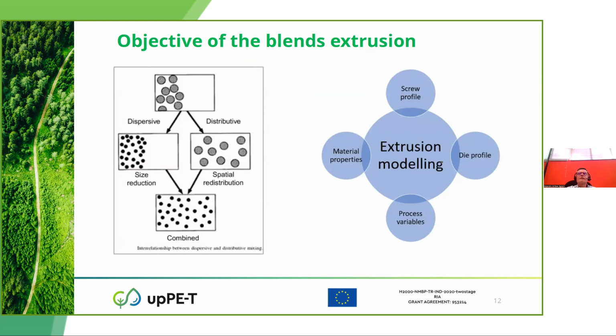How to reduce the additive agglomerates, such as small polymer portions? That is, it should provide dispersive mixing, as in the left figure. Once the small polymer portions have been broken up, then a uniform distribution, that is a random spatial orientation of the dispersed polymer, is required. This is known as distributive mixing. The two mixing processes are not totally separate. When dispersive mixing is performed, there is always some distributive mixing, but the converse is not always true.